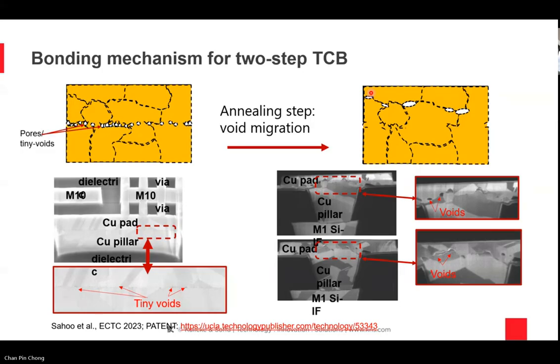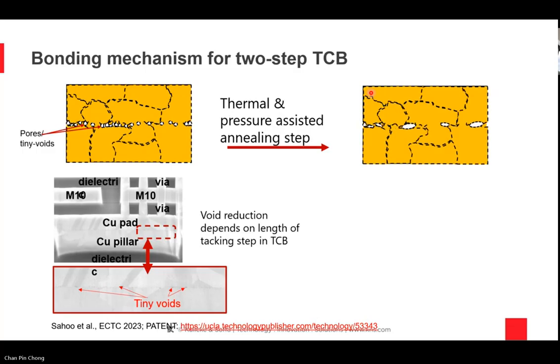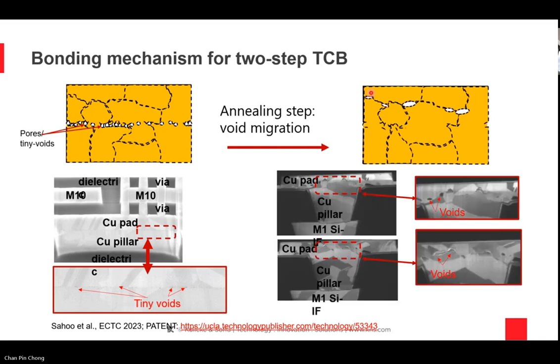And again, remember that our focus here is on die to silicon substrate bonding, which is going to be the most important type of assembly going forward. So we've actually done lots and lots of reliability studies on this, the temperature, humidity, and so on and so forth, and we don't see any fundamental problem in the reliability of these thermal compression bonds. And we have done this with commercial chips. We get these chips from TSMC, we get these chips from GlobalFoundries, and so on and so forth. And there is no issue at all.